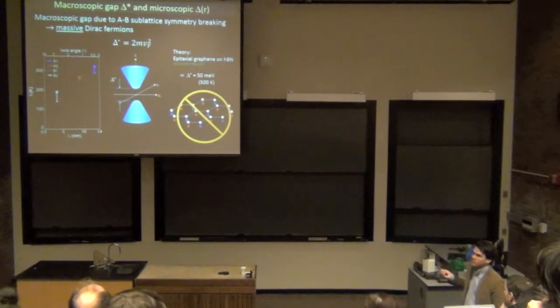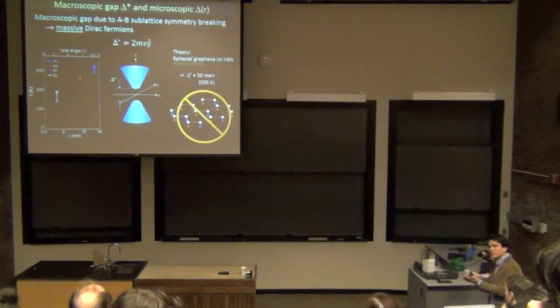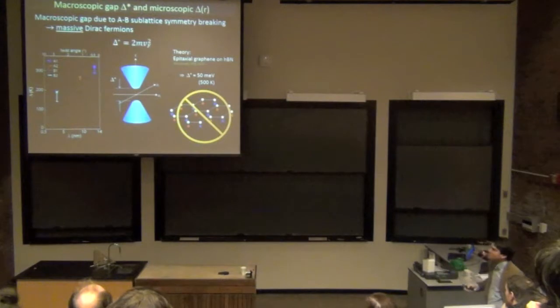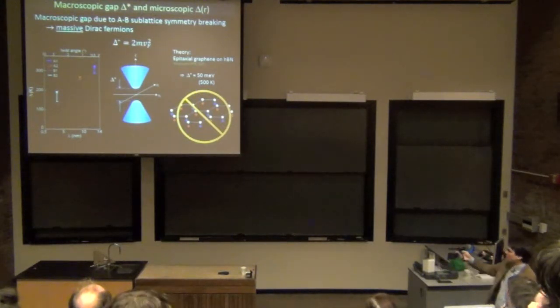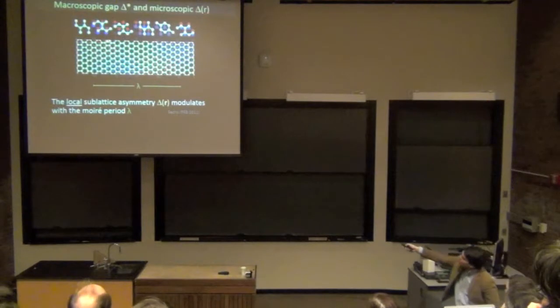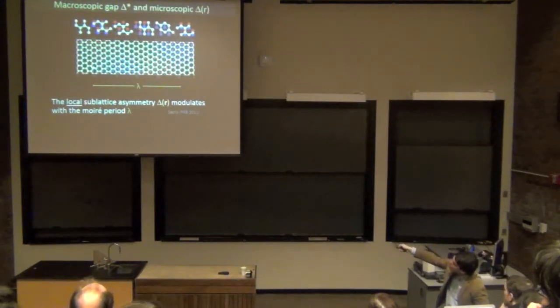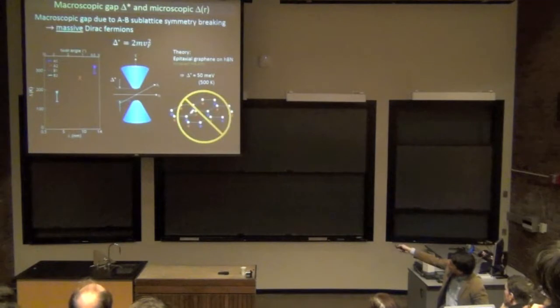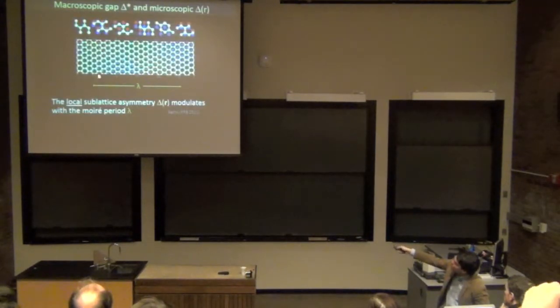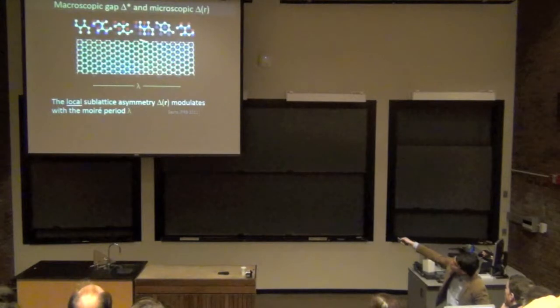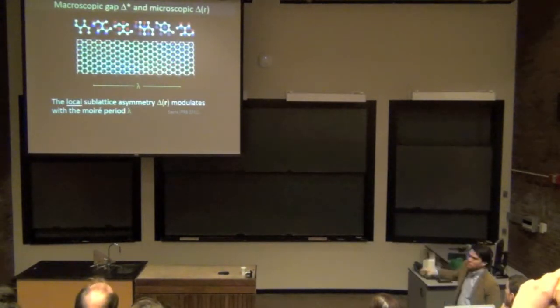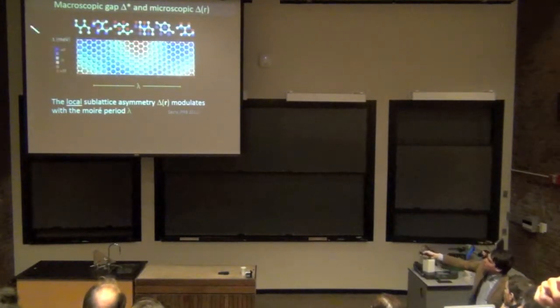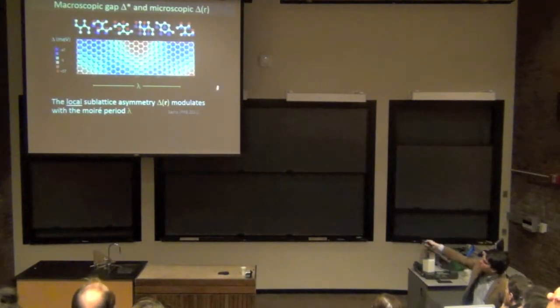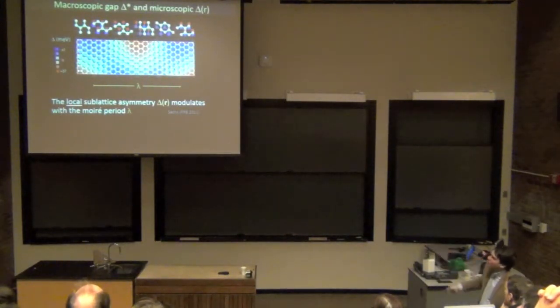I told you before that the graphene and boron nitride are 2% different in lattice constant, and we know that there's a moiré pattern, right? And this moiré pattern, if you look in detail at a microscopic model, looks like this picture: perfectly aligned graphene and boron nitride, only in certain areas. You can see this corner up here and down here, but the overall modulation of the alignment is different. And what that results in is a gap, or a mass, that oscillates with the period of the moiré.